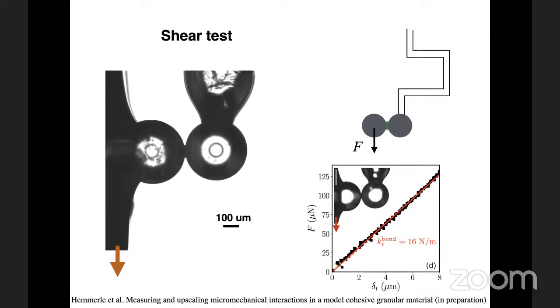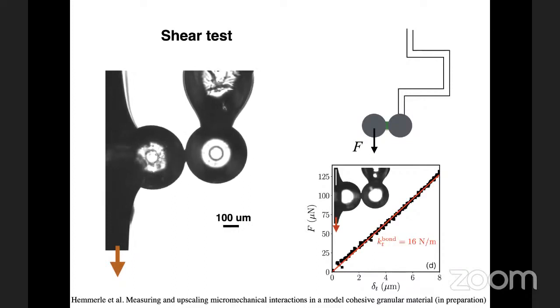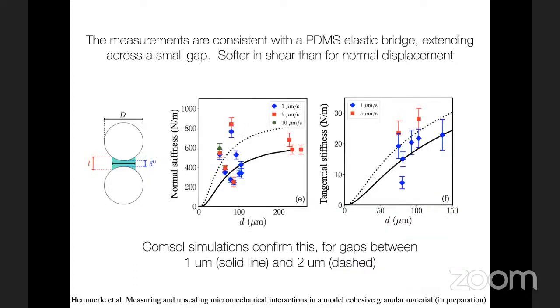What we find is that the shear spring constant, the shear mode, is much softer than the normal mode. So if you look at the shear stiffness, it's of order 10 newtons per meter. The normal stiffness is of order 100 to 1,000 newtons per meter.